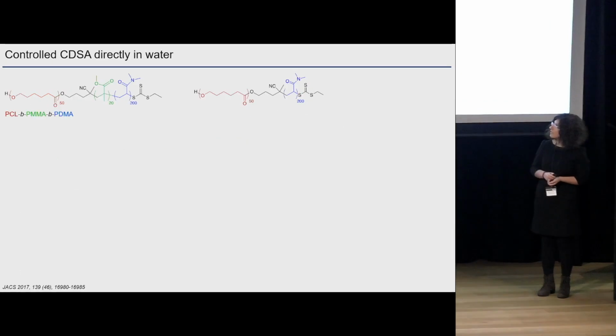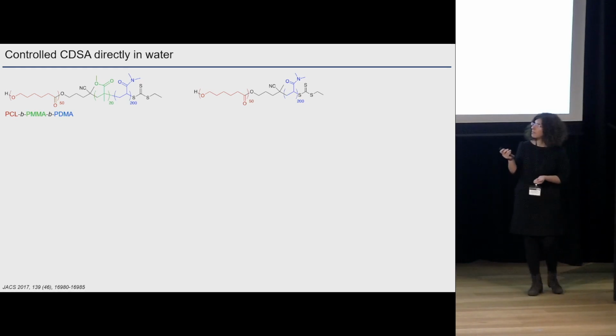So to overcome this, we designed a slightly different polymer. I put here for comparison the one that I was talking about before. It has this polymethylmethacrylate block. It's a very short block of only 20 units, but it is a very hydrophobic, very glassy polymer. Basically, what it does, between the hydrophobic component and the hydrophilic component, is to protect the crystalline core from collapsing. And so in this case, the nanoparticles shouldn't collapse when transferred into water.